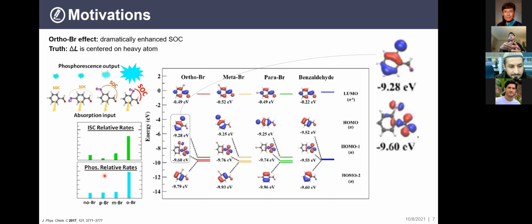And we found that when bromine is in very close proximity, in the ortho position to the carbonyl group, this will give us the highest rate. But we failed to summarize the reason. When I looked back into this paper, I found the reason is that you see this orbital here is contributed from bromine, from the in-plane non-bonding electron of the bromine. Because it's very close to the carbonyl, the non-bonding electron interacted with the carbonyl's non-bonding electron. And in this HOMO orbital, it is going to the out-of-plane direction. So this HOMO-1 to HOMO transition will give a very large spin-orbit coupling value, which affects the intersystem crossing phosphorescence rate of this type of material.